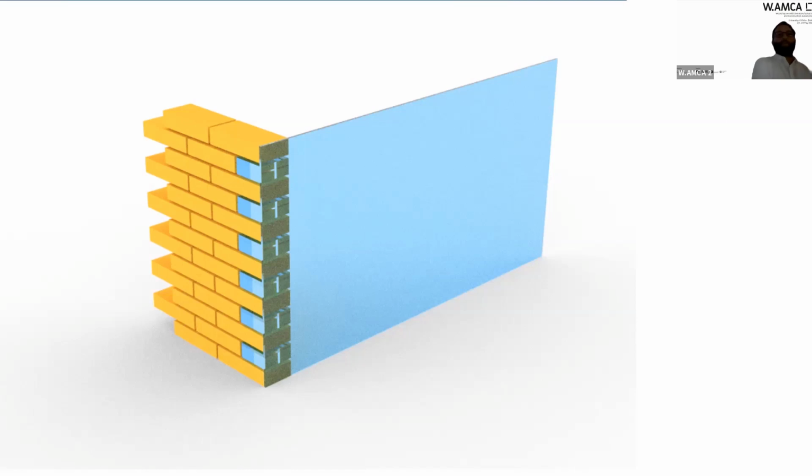There's a sheet material called Surlyn, which is very transparent. It's easy to form under a very low amount of heat. So basically, with a heat gun, you can just put it on top of the sheet material, heat it, and then it stays in the same shape, but it's still a dry connection. So you can use it for masonries. But yeah, you can also just use silicone as a fixed glue.